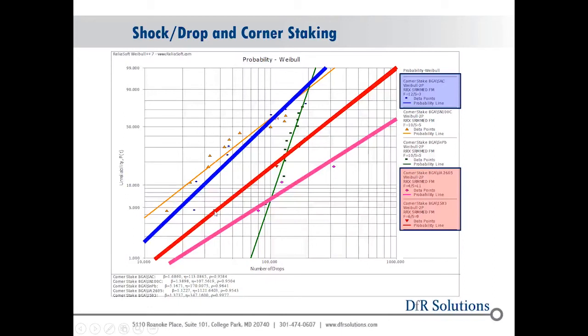Looks like there was one early failure here on the red, but definitely purple, there's only 3 failures. In fact, you can see there's quite a bit of number of suspensions here. So definitely the corner staking had a significant impact on drops to failure, where we were getting drops within 20 cycles. Now we're starting to get drops 70 to 100 before we see the first failure.